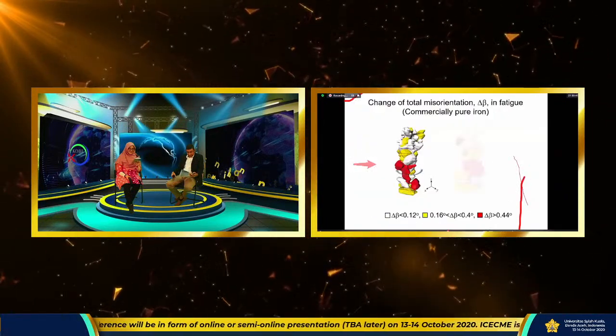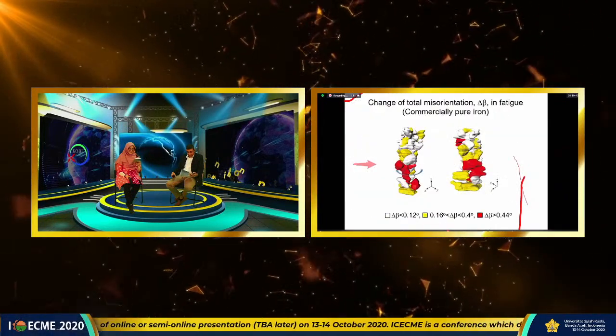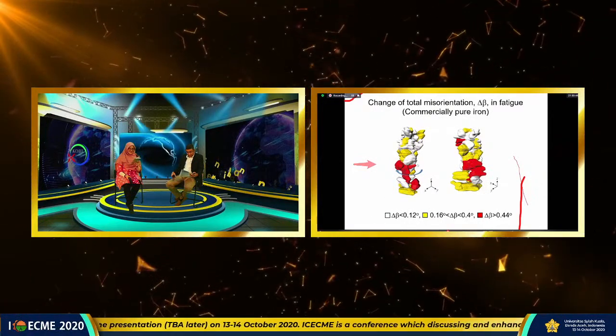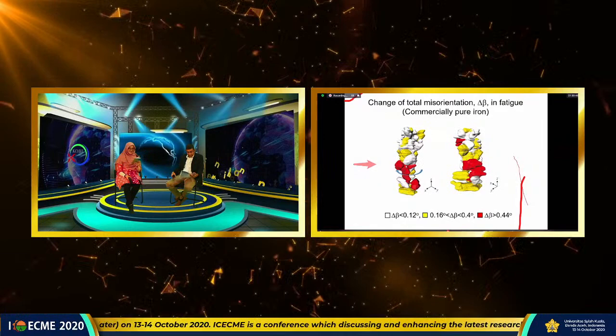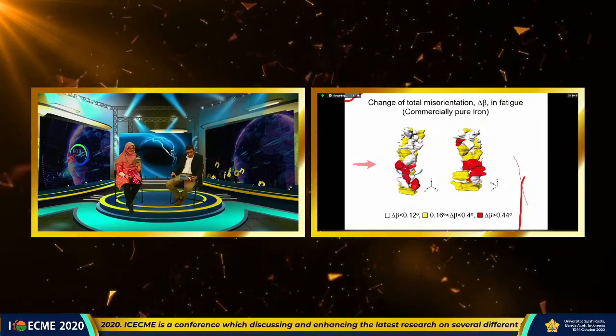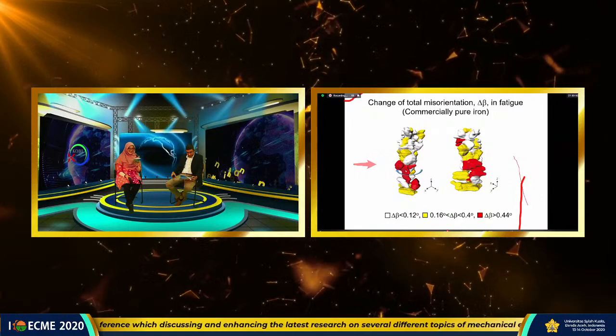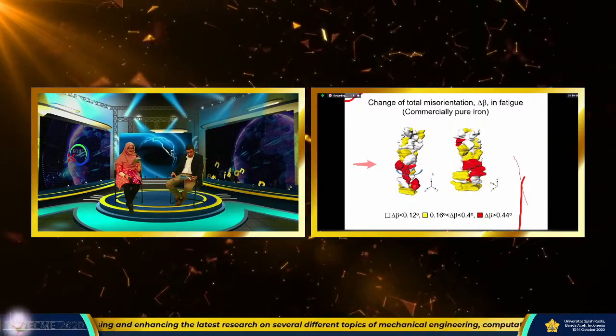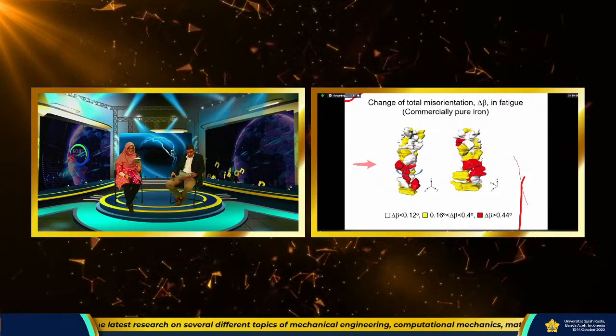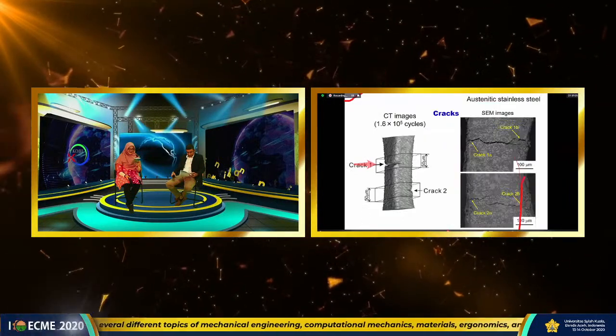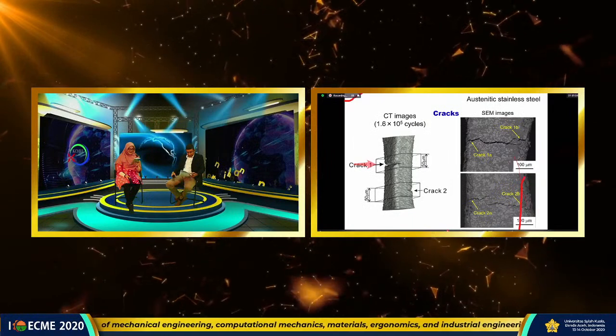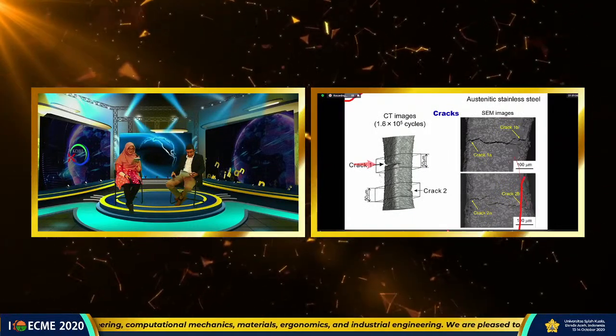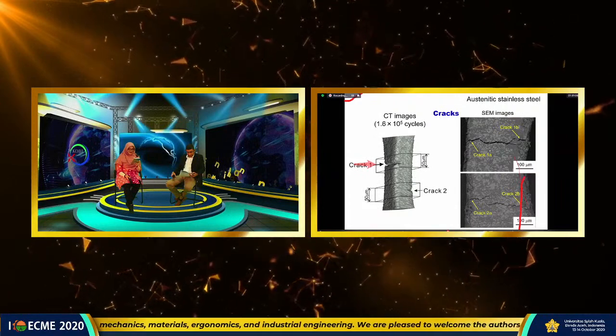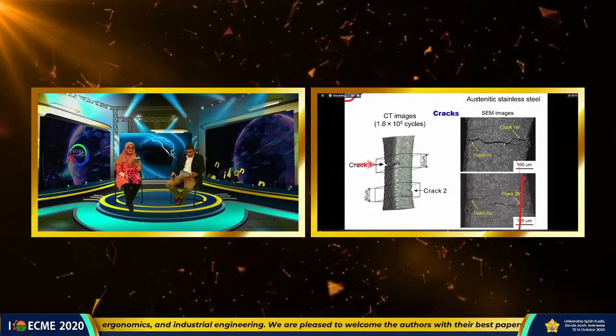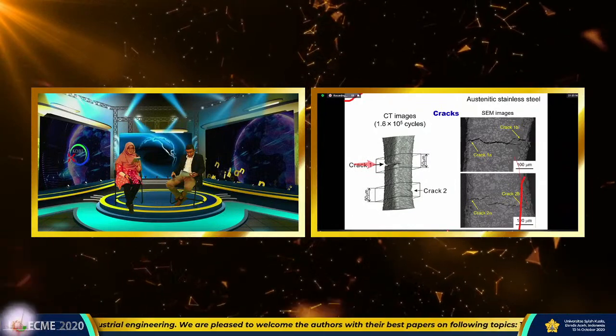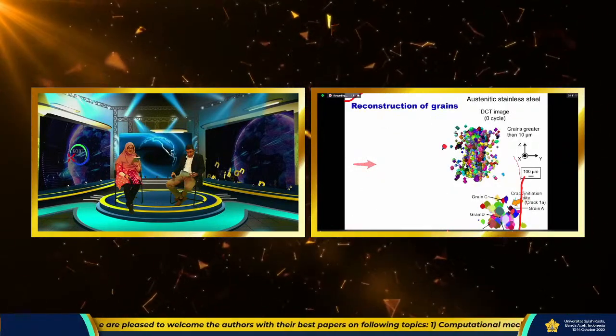Next I'm going to talk about diffraction contrast tomography. This is a change of misorientation. The change of misorientation during the fatigue process is different for each grain, and the cracks may initiate from a large change of misorientation like this. This is another material. We have a CT image of cracks. It's an SEM image from the surface. We have a crack like this and like this. And it's a diffraction contrast tomography for this material.